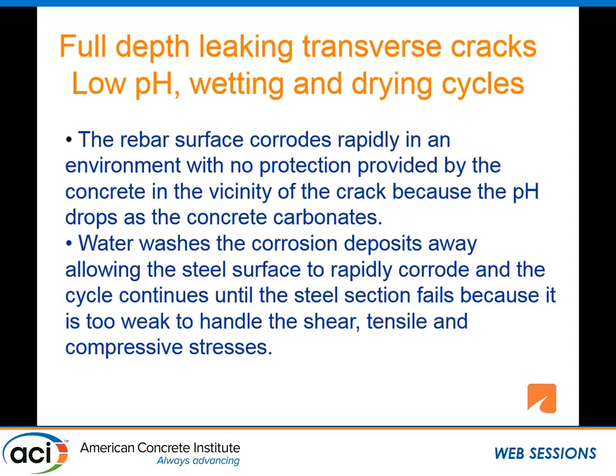In these full depth leaking transverse cracks, the concrete quickly has a low pH and it's subjected to wetting and drying cycles. The rebar surface corrodes rapidly. There's no protection provided by the concrete in the vicinity of the crack. Water washes the corrosion deposits away, allowing the steel surface to rapidly corrode, and the cycle continues until the steel section fails because it's too weak to handle the shear, tensile, and compressive stresses.